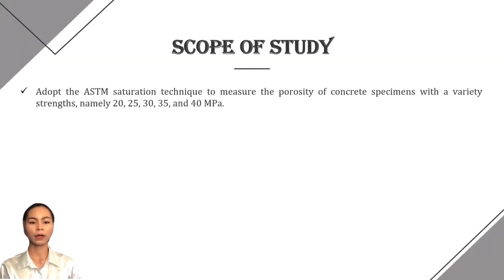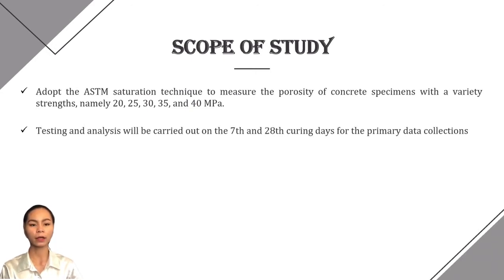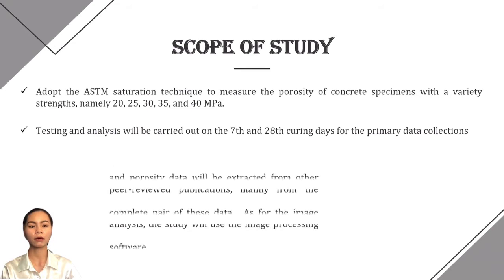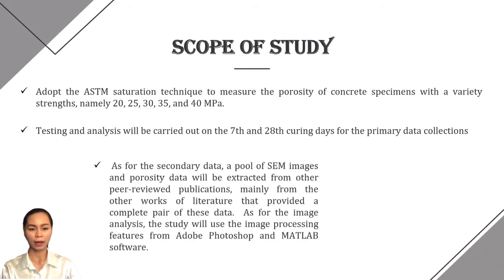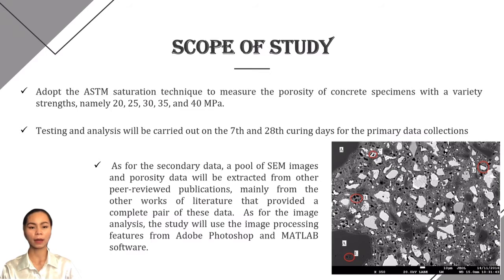In this project, I will adopt the ASTM saturation technique to measure the porosity of concrete specimens with a variety of strengths, namely 20, 25, 30, 35, and 40 MPa. The testing and analysis will be carried out on the 7 and 28 curing days for primary data collection. As for the secondary data, a pool of SEM images and porosity data will be extracted from other peer-reviewed publications which provided a complete pair of this data. As for the image analysis, the study will use the image processing feature from Adobe Photoshop and also MATLAB software.